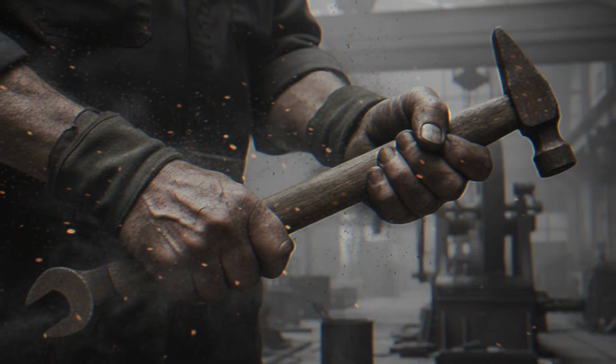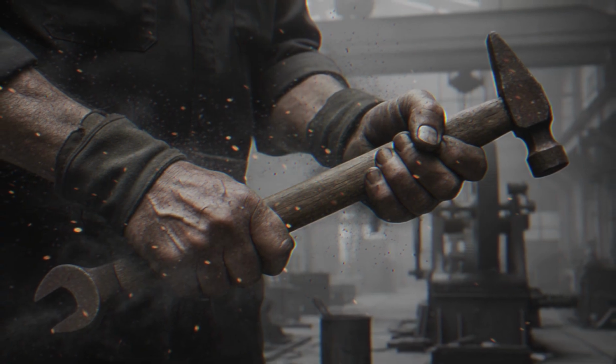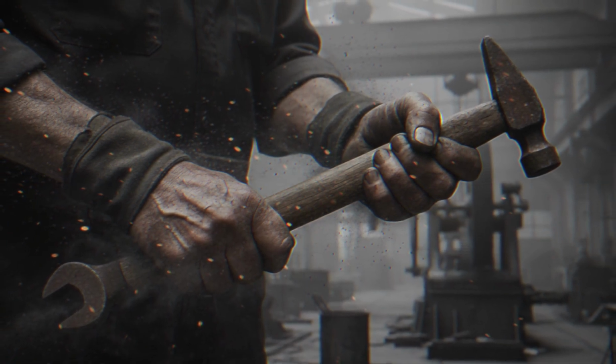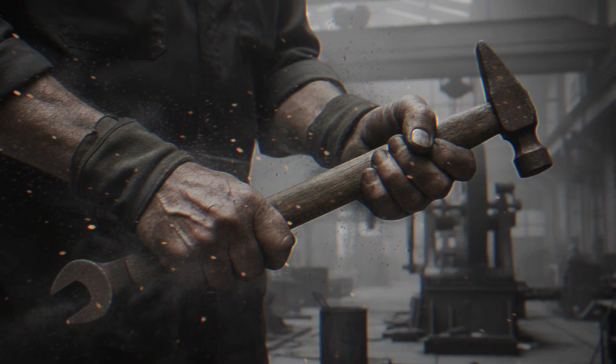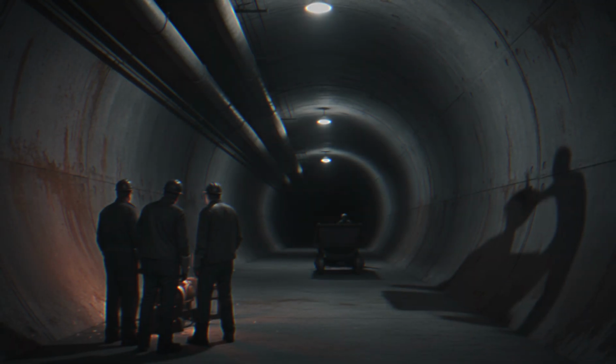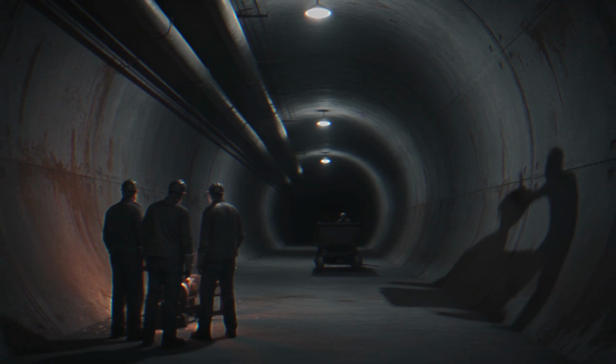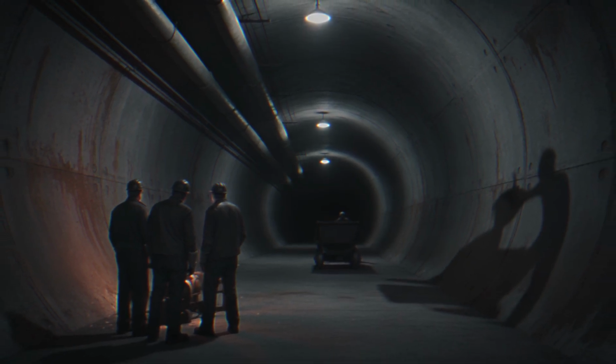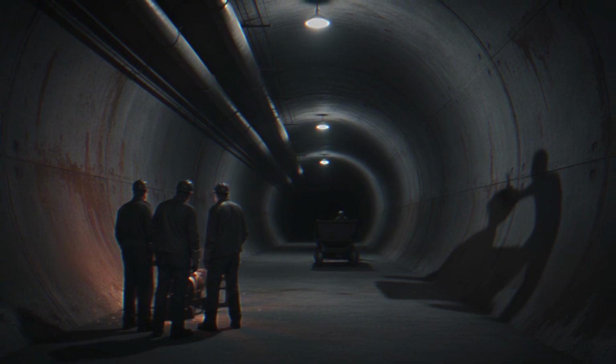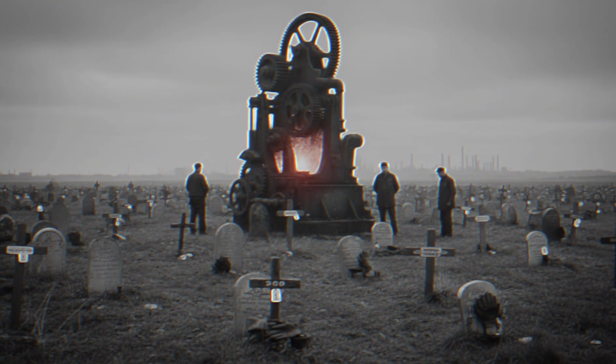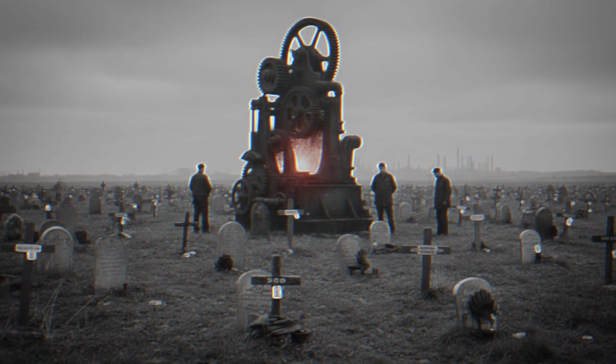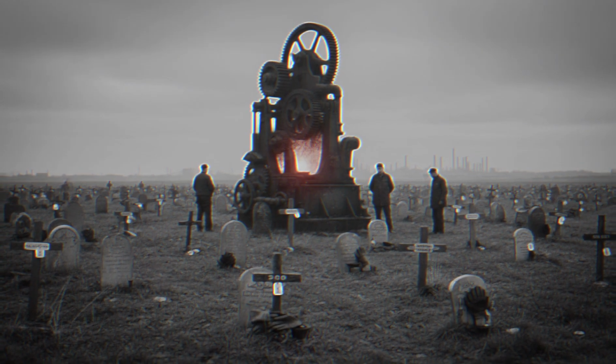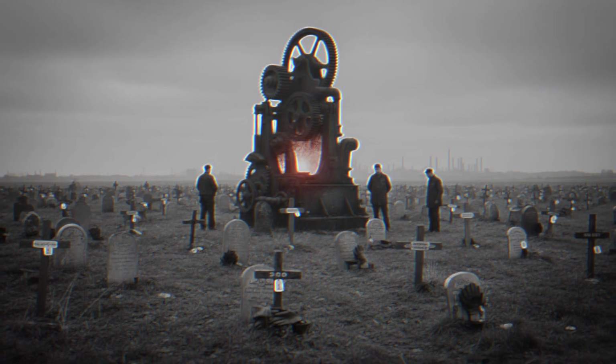The riveted construction of the furnace shell itself presented a separate long-term integrity problem. Individual rivets could be checked visually for head condition and driven condition. What could not be checked visually, without removing them, was the condition of the shank passing through the plate. Corrosion from the outer surface of the furnace shell, particularly in the stack section, above the tuyere zone where condensation of process moisture was possible, could attack the rivet shanks over years of operation.